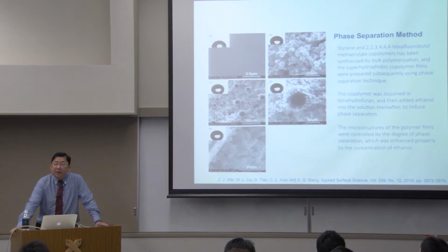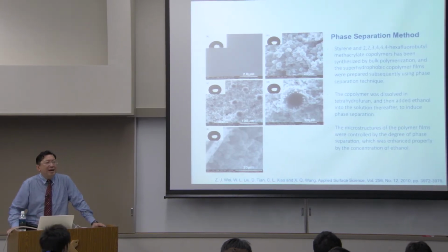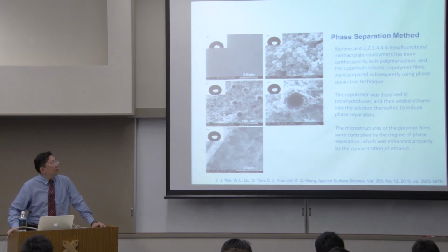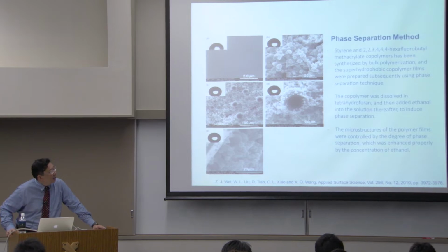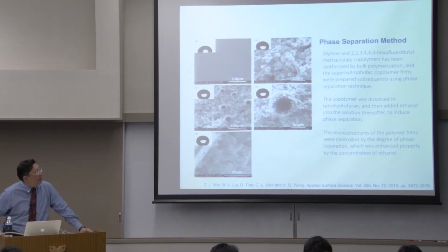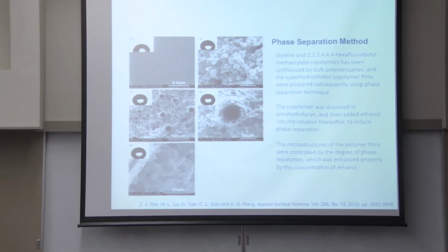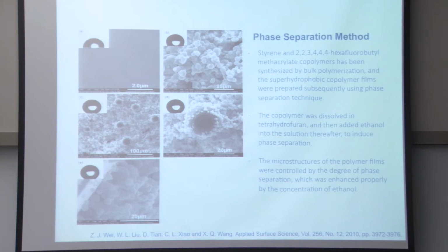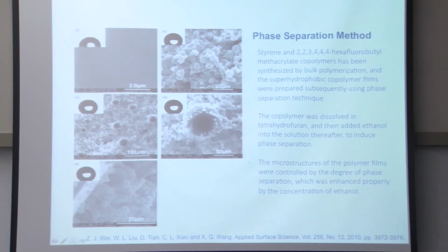Another method is based on phase separation, which can be done with liquids or polymers and liquids that have an immiscible property. In this case, styrene and a copolymer were prepared in bulk, and because of their phase separation when dried as a film, they form these morphologies. These microstructures are based on the inability of the copolymer to separate itself between water and THF. After drying, you end up with a surface like this, and the microstructure of the polymer film results again in superhydrophobic qualities as shown in these systems.